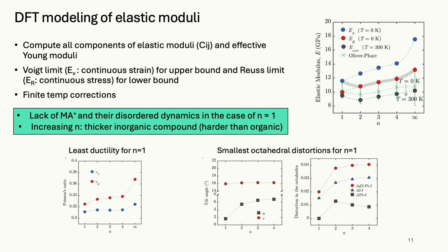And so the continuous strain limit is more appropriate for n equals 1, whereas we use the Reuss limit for the rest. We're quite happy with this level of agreement, but then we realized that these simulations are at T equals 0. It's well known in the literature how to correct elastic moduli from 0 temperature to make a finite temperature correction. And so when we apply that correction, we go from the gray line that we calculated from DFT, and you have this more or less rigid shift. And so the results agree rather well with the experiment, but they're a little bit of an underestimate.